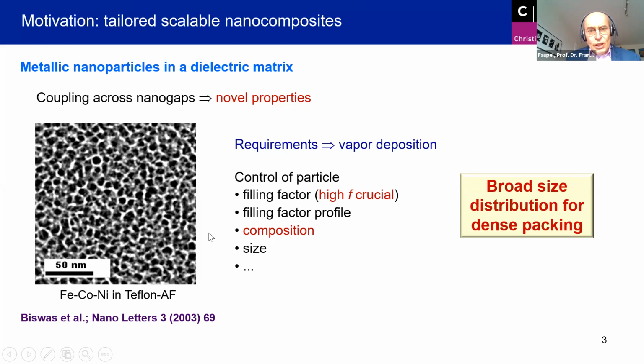Yeah, in addition to tailoring the filling factor, sometimes you also need gradients. I will show you examples. And not only do we have to tailor the gaps here on the nanoscale, we also have to control the alloy composition of the particles. And this will be done, among other techniques, with this gas aggregation cluster source, which I show you in a moment. And also we need control over particle size, at least averaged over a large ensemble.